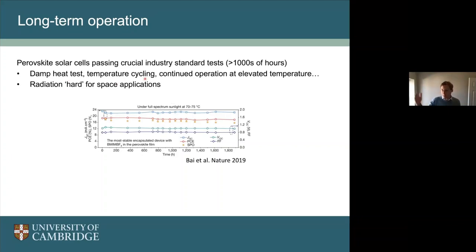We also do things like temperature cycle from very high temperature to low temperature and back up. And we need to check even in these very high stress conditions that they pass these tests, and therefore they're ready for the next applications. And so this is an example, some data where we look over many hours and looking at the efficiency, which is in red here. And you can see this is a cell that is very stable. So over 2,000 hours, which is several months, it is operating very well, even at very high temperature, which is very promising.